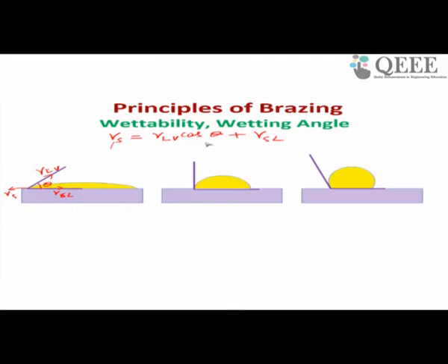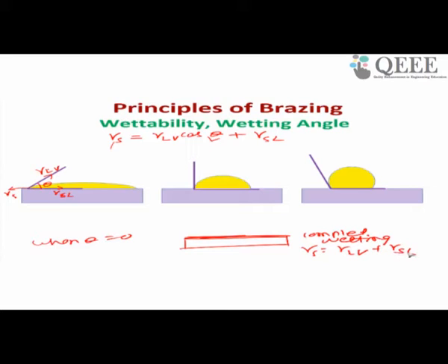Now, when complete wetting is possible, what is desirable? Desirable is complete wetting. When theta equals 0, it can completely wet. Okay, so complete wetting. In this condition, when theta equals 0, gamma S equals gamma LV plus gamma SL. It means for complete wetting to happen, the surface energy of the solid should be equivalent to the summation of the surface energy of liquid-vapor plus the surface energy of solid-liquid.